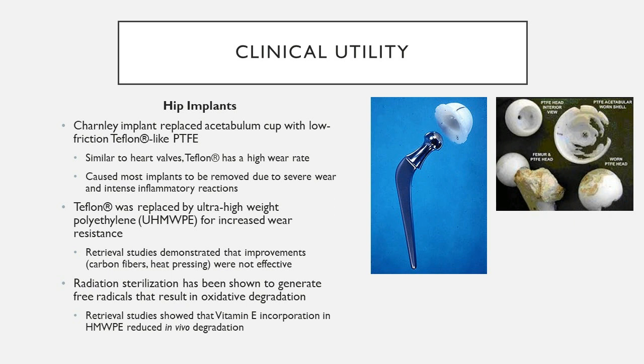Later retrieval studies showed improvements to device design by incorporating antioxidants. Note, my personal choices would have been blueberries and those from pomegranates. However, biomaterial engineers tend to use something a little bit more practical like vitamin E. These antioxidants showed improved resistance to oxidative degradation in vivo.